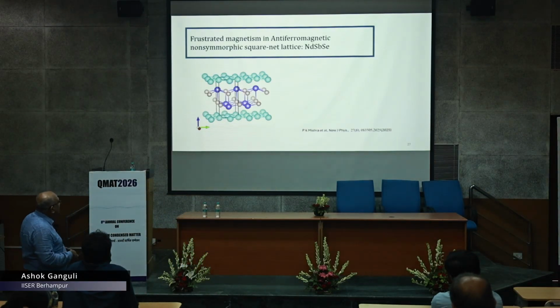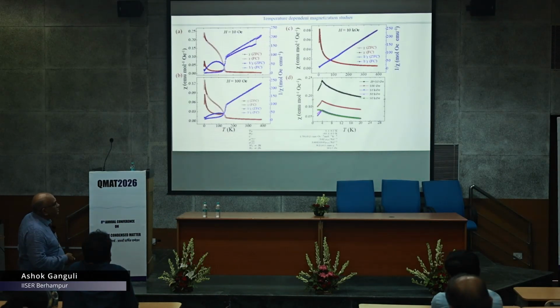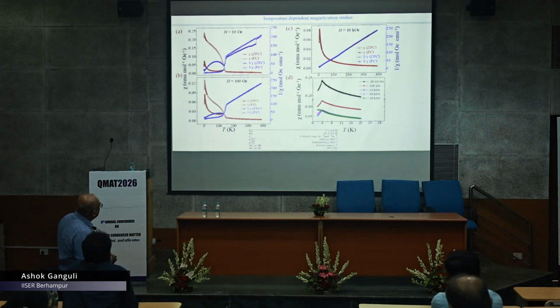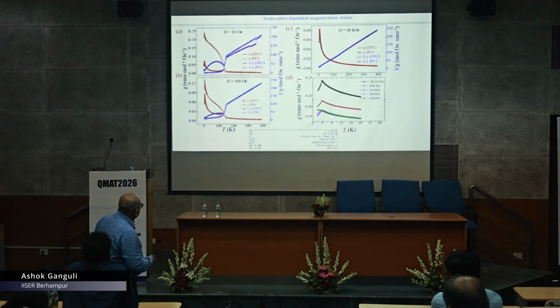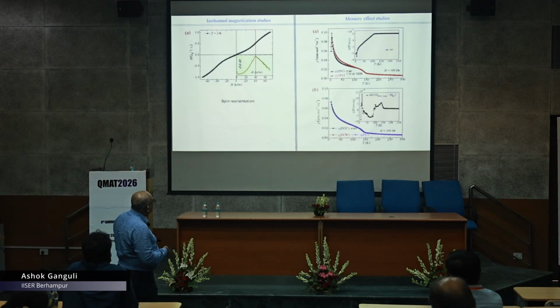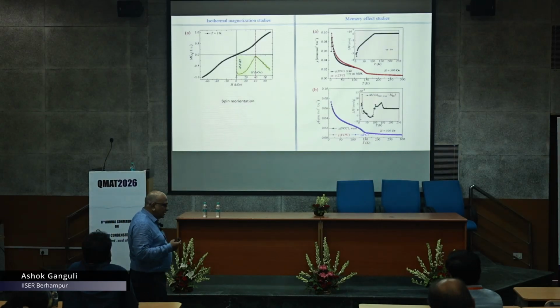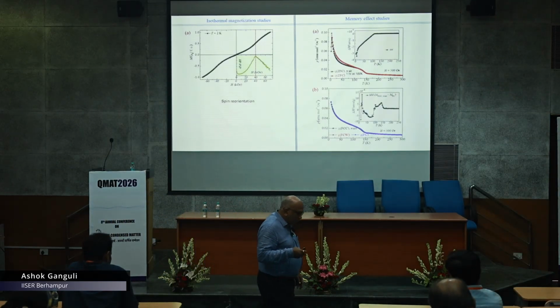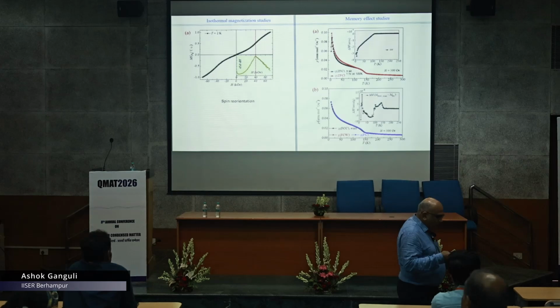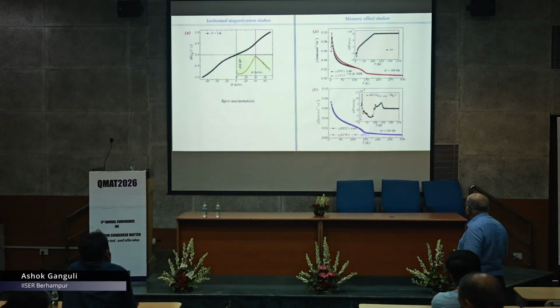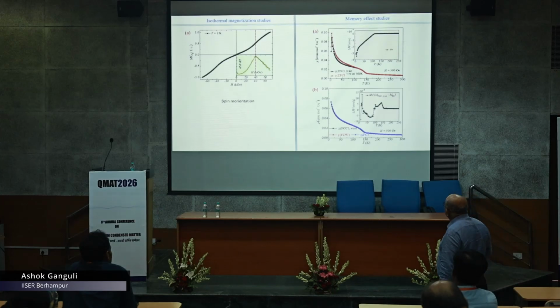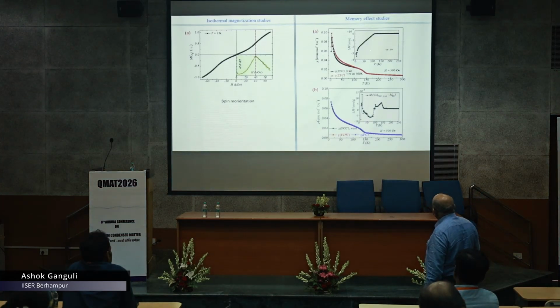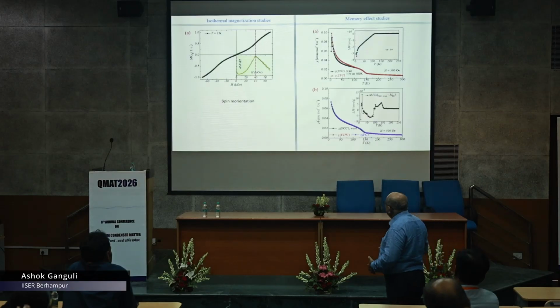This is another case. That was NdBiTe, this is NdSbSe. So this is antiferromagnetic again, and here TN is around 4 Kelvin. Most of them are at low temperatures. Here we studied this memory effect, where you stop while field cooling. We also did ZFC and waited for some time, nearly an hour at 100 K, and found the difference and plotted the difference at 100 K. So there are memory effect studies.